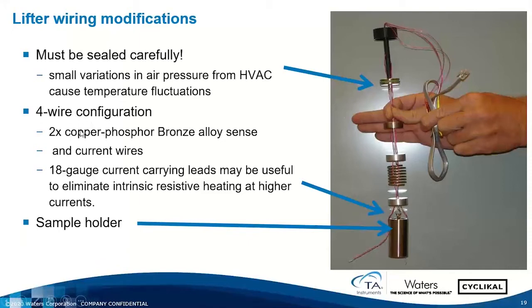And we use copper phosphor bronze alloy wire. It's low thermal conductivity wire. It's double braided. Each strand is approximately 32 AWG, American wire gauge, thickness. We use the double-stranded copper phosphor bronze alloy for both the sense and the current wires. In the past, it may be useful for certain applications to use a lower gauge, thicker wire for carrying the current to eliminate intrinsic resistive heating in the wires at higher currents.